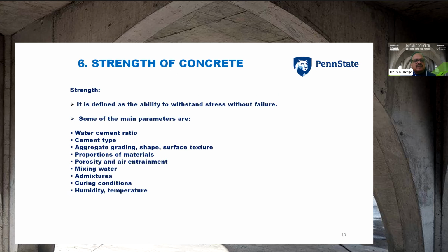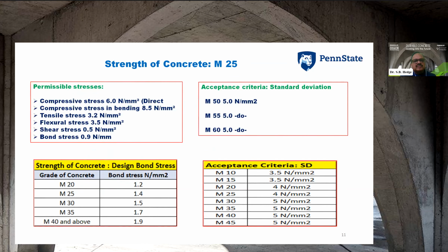So what are all the factors responsible for the strength of the concrete? If you see, the major things, as you are aware, the water cement ratio plays a very important role. Then comes cement type, aggregate grading, shape, surface texture, proportions of materials, porosity, air entrainment, mixing water, admixtures, curing conditions, humidity, and temperature. All will have a direct effect on the strength of the concrete.